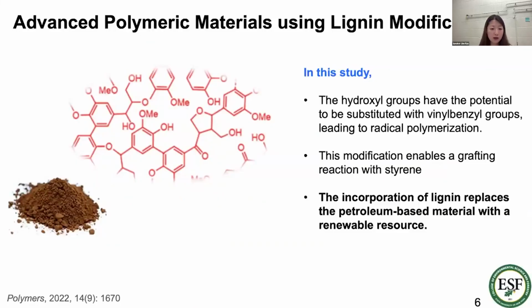So in this study, our motivation and purpose is to replace petroleum-based polystyrene with lignin material. We use hydroxyl group modification for radical polymerization. We have the hydroxyl group in the lignin structure, and by introducing the vinyl benzene group into this hydroxyl group, we can use this functional group as a radical polymerization resource, similar to the styrene structure. Modification of lignin enables radical polymerization with styrene together, so we can make lignin styrene copolymer.